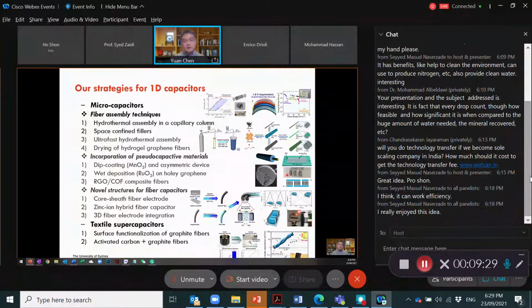And there are also issues about how to incorporate other material into the carbon composite, because the carbon material itself sometimes has relatively low energy storage capability, so we need to add other material in. And adding material in is not trivial, because if you add too much, they will block the pores, and if you add too little, then they don't have much effect. So we're actually developing different approaches to incorporate them together.